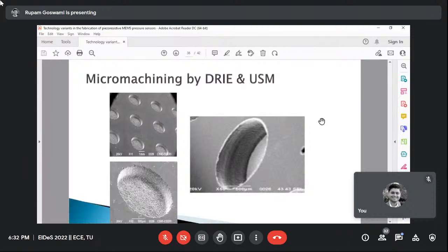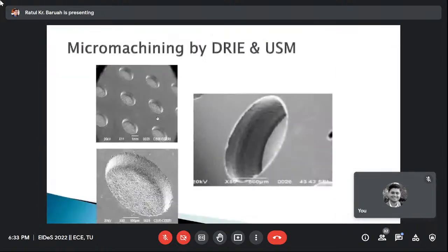So you will see that in making these cavities by anisotropic etching, it takes 9 hours or so. But if you use USM or this kind of technique, it takes very little time, even minutes. But the sample preparation also consumes a lot of time. But these are the things, and we can bring technological changes in the process. Next, please.